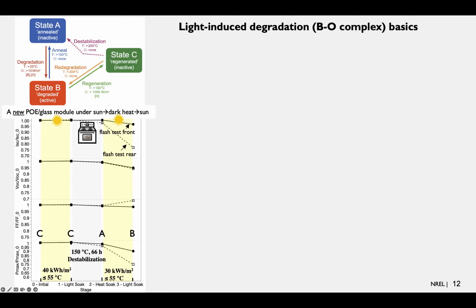So one would assume that this is a state C, regenerated inactive state, or, you know, it just doesn't exhibit light-induced degradation. Then we did a destabilization sequence to understand if it adhered to this model, whereas if we destabilized it, we would lose power. And sure enough, at 150 degrees C, 66 hours destabilization sequence, we see a little bit of degradation. And then when we put it under light again, in this case less than the first time, 30 kilowatt hours per meter squared as opposed to 40, we see an important amount of degradation.